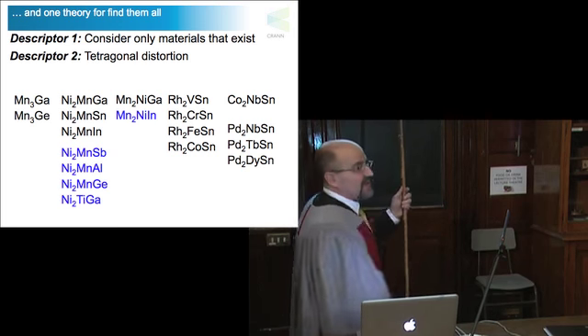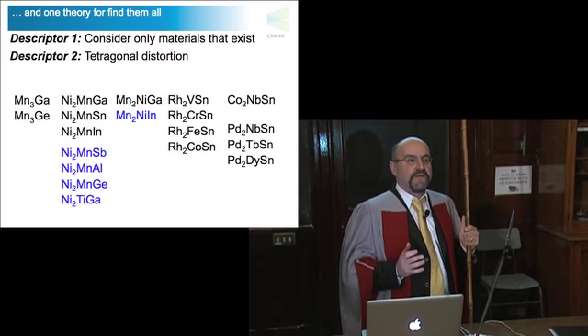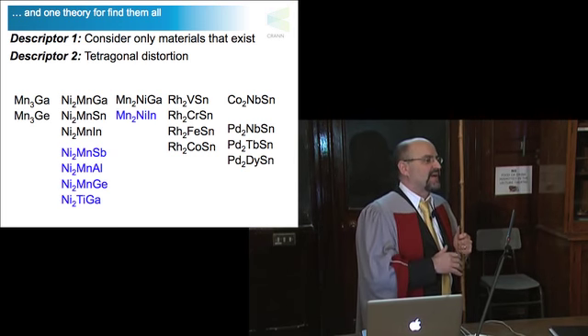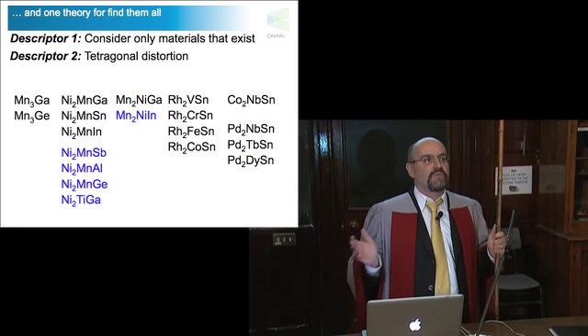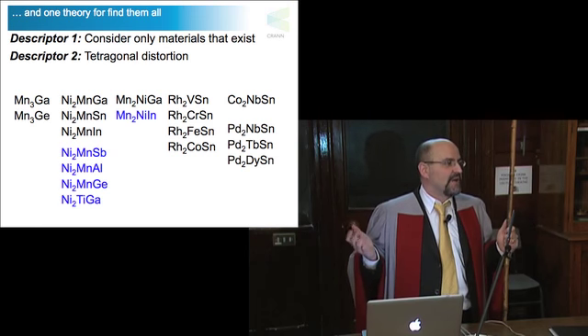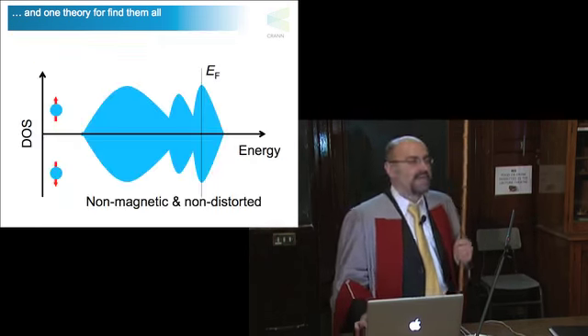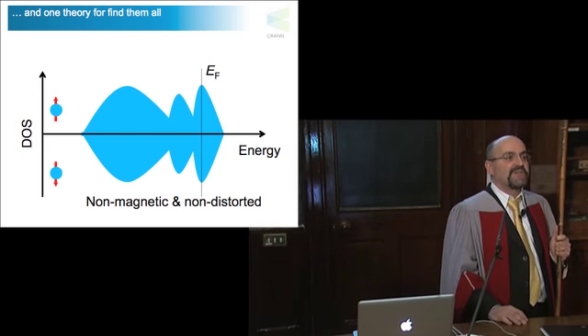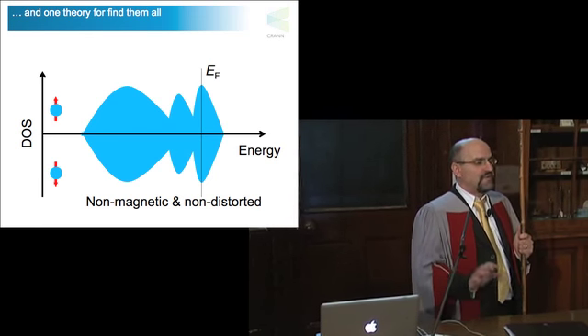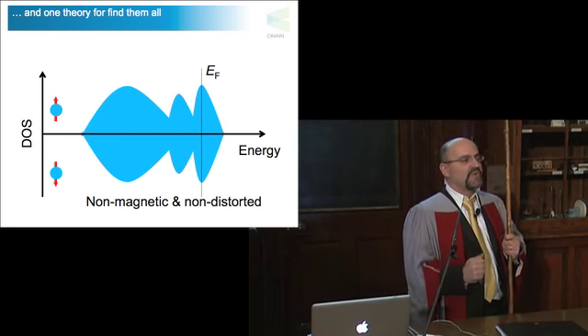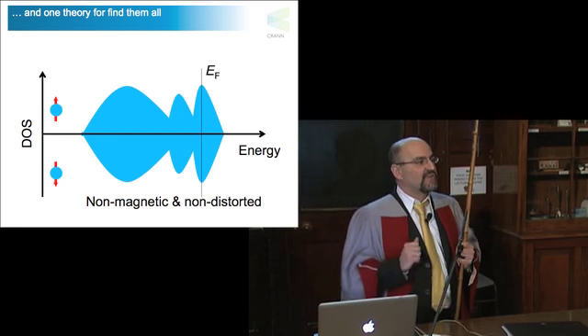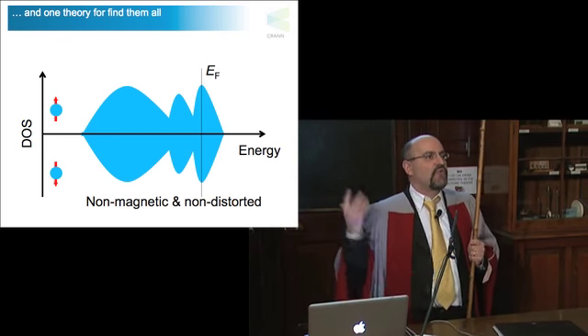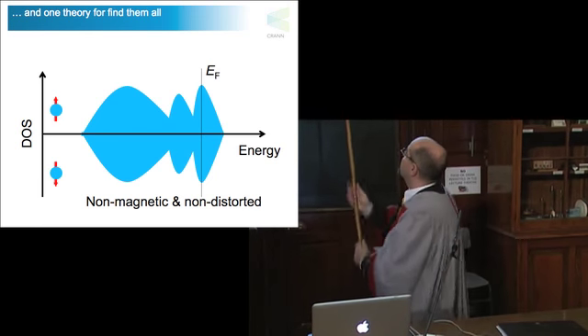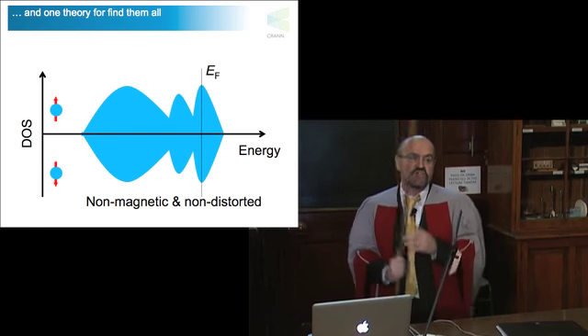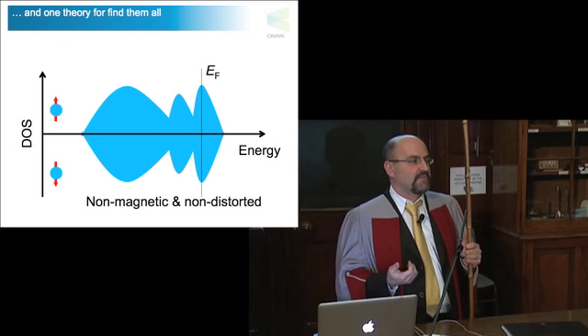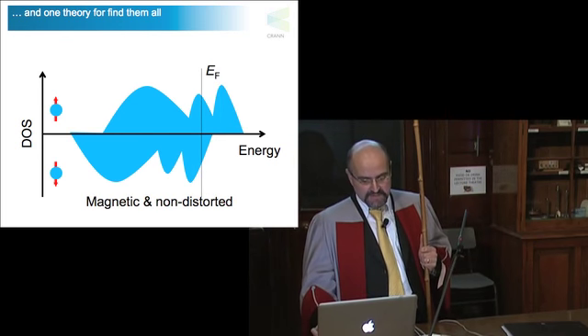Now, if you look at those materials, honestly speaking, I really challenge you to find a commonality. They come from any region of the periodic table. Some of them are magnetic, some of them are not. Honestly, when we started to look, with Tom here, we couldn't find a particular reason. But then we went to the database, we looked very carefully, and what we found is that they all follow this particular story. If you calculate them and you fix the atoms in a non-distorted situation, and you impose by brute force that these are not magnetic, you find the density of states almost always looking like this. Now, for those of you who know how to read these things, when the density of states is like this, so you have a big peak at this particular critical energy, which is called the Fermi energy, the material usually will try to spontaneously generate magnetism. So, in fact, almost all of those become magnetic.